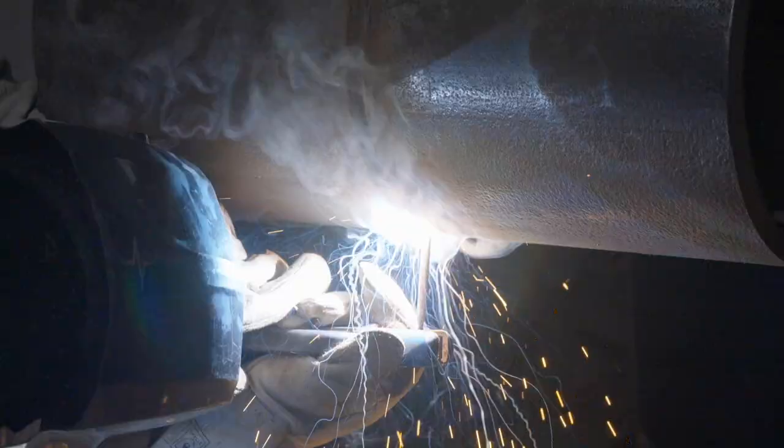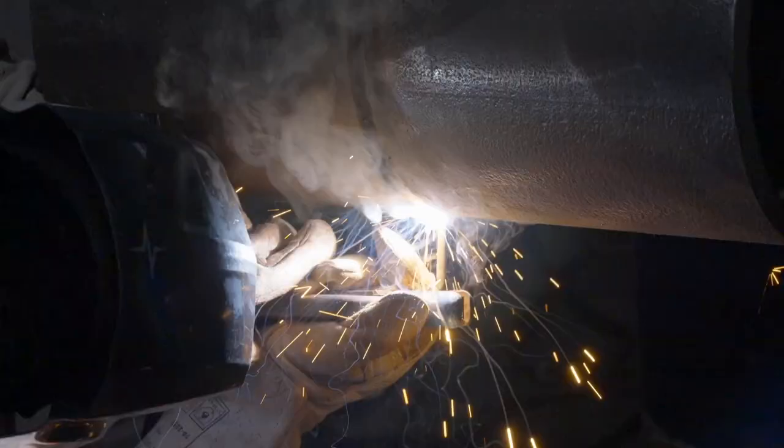During the overhead position, the welder should try to end at the 6 o'clock position and the electrode angle should not be too much inclined. The cap is deposited with a slight weaving technique with a maximum weave of twice the electrode diameter.